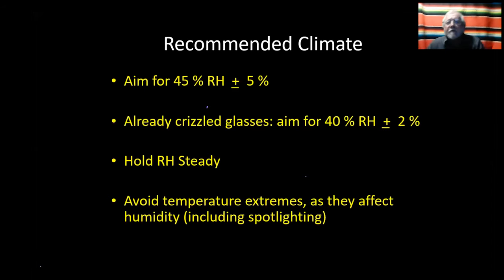So, storage. Glass is a sensitive material. It's not really as stable as we would like. I have seen some glasses that have suffered over prolonged storage on archaeological sites, and that's primarily because those archaeological sites have no climate control whatsoever. But in a museum, we should try to aim for a controlled climate. And we've recently just published this: aim for 45% plus or minus 5.